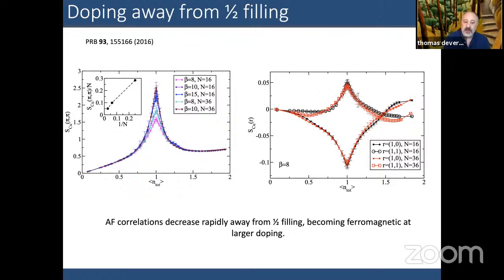And if you look at the real space correlation, that's S of R at different coppers, and you look at the sign of that as a function of doping, for nearest neighbors, it's R of (1, 0), or next nearest neighbors (1, 1), that of course is negative at half filling, but then when one dopes, one can see that there is a sign change that occurs, and that's because the magnetic correlations tend to become ferromagnetic as one gets to larger doping. And of course, I'm showing you here doping ranges which are well beyond what we normally think of in the cuprates, but I'm just showing you the full range from the empty band to the full band.